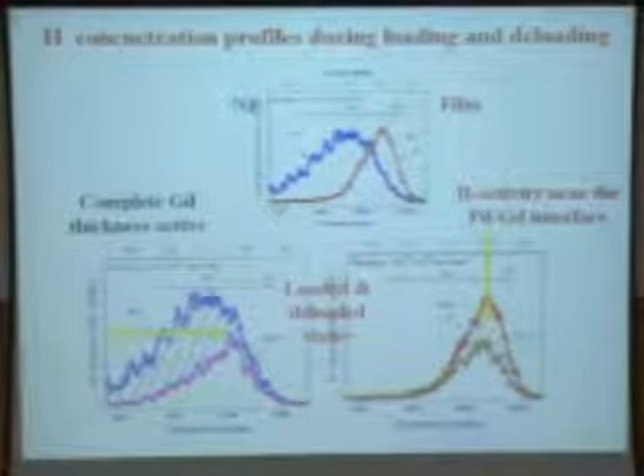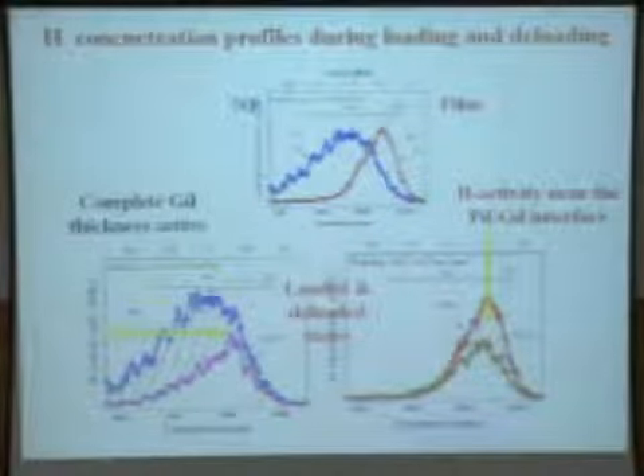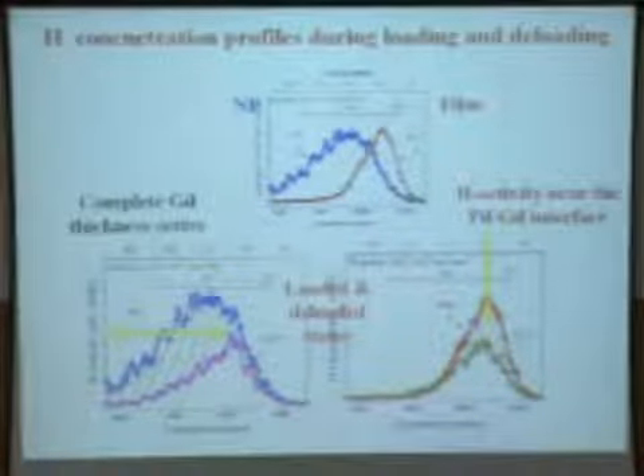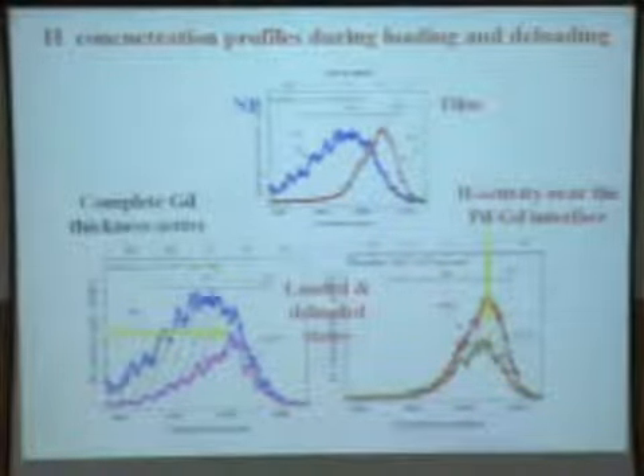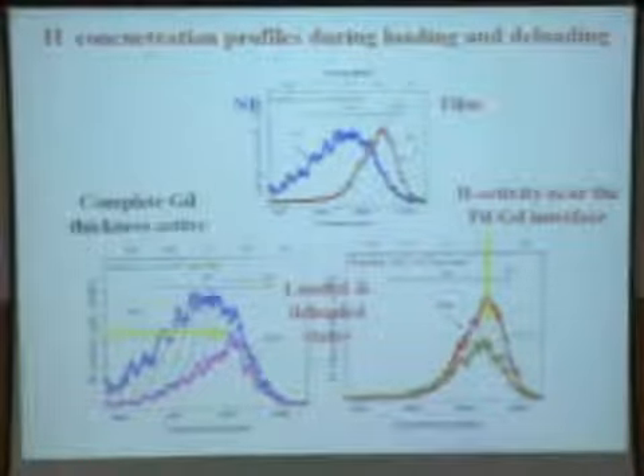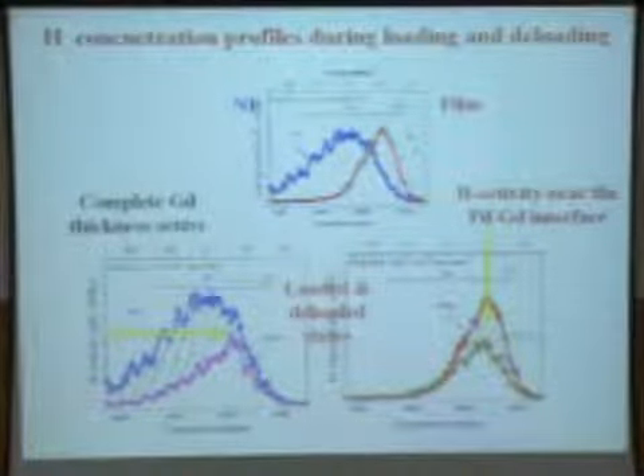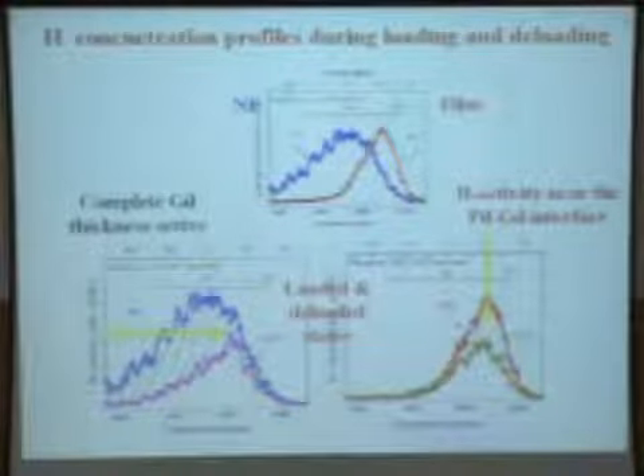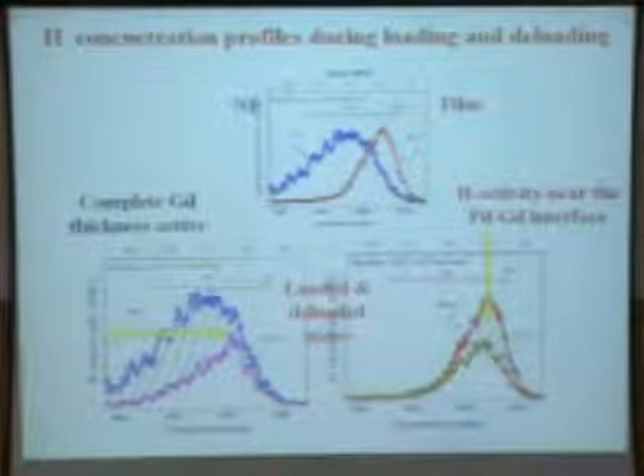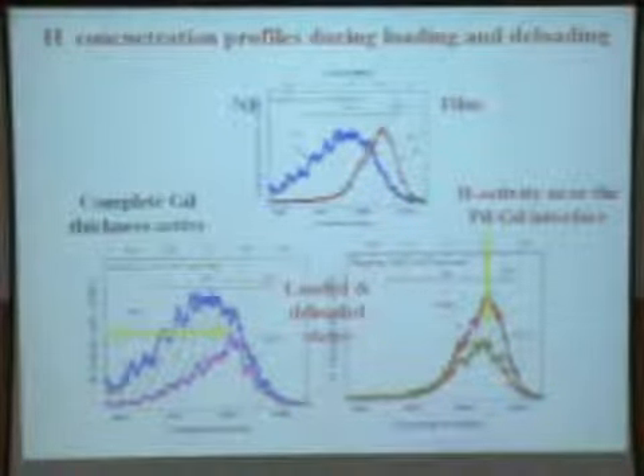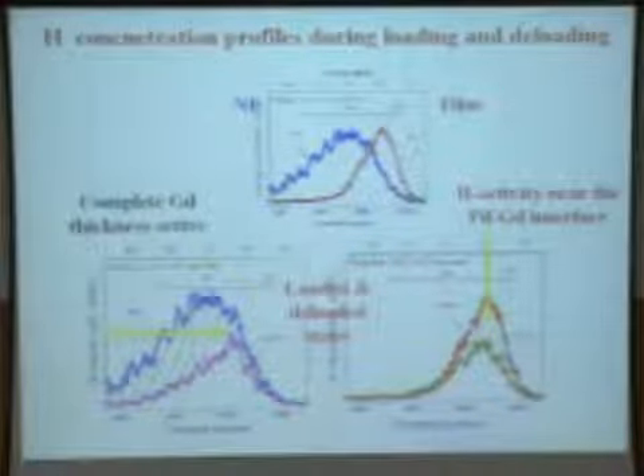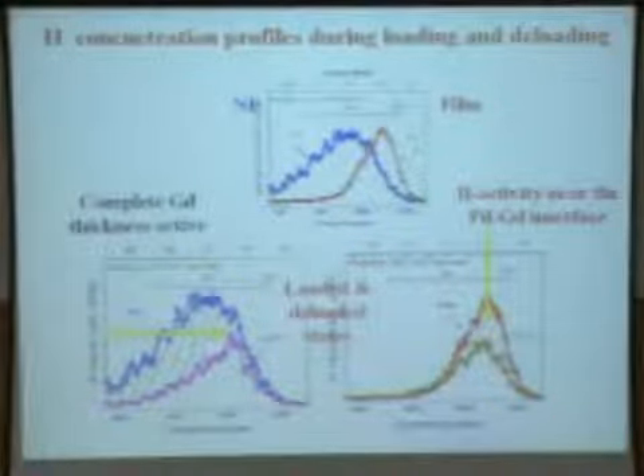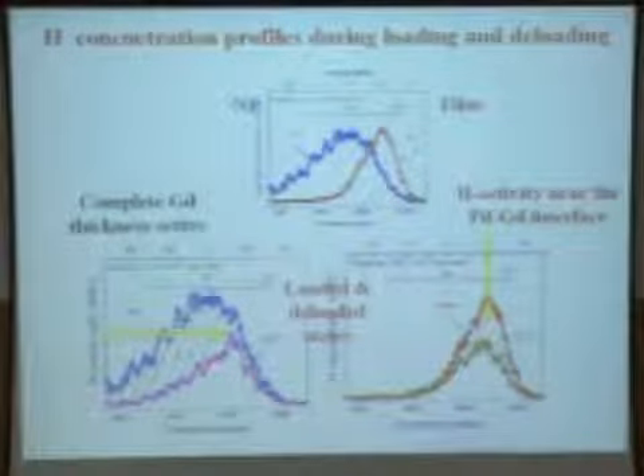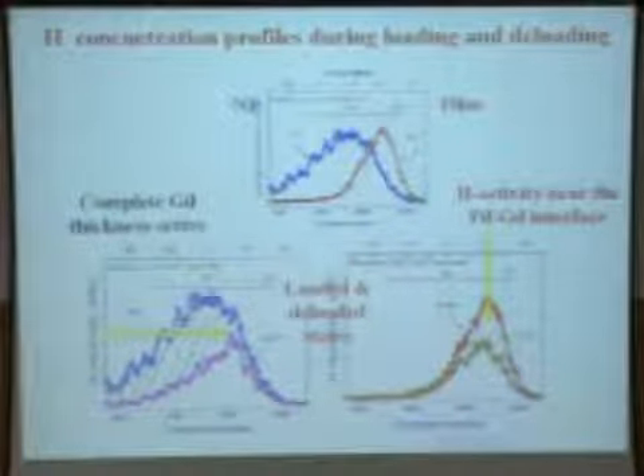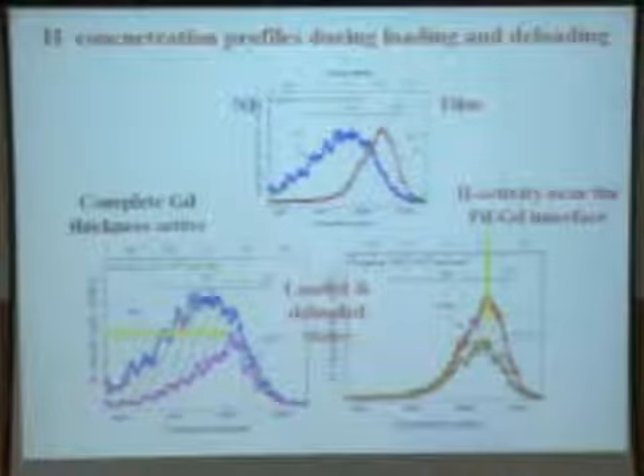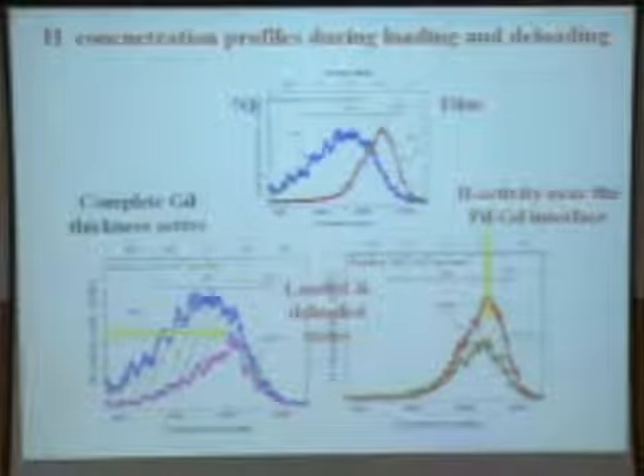So this is another experiment we did, where we wanted to investigate what is causing this improvement. This is an experiment done using a technique called elastic recoil detection analysis. This is a technique where you can measure the hydrogen concentration in the material and also the hydrogen concentration profile in the material. And you can see that in case of a nanoparticle layer, this is the loaded state and this is the deloaded state.